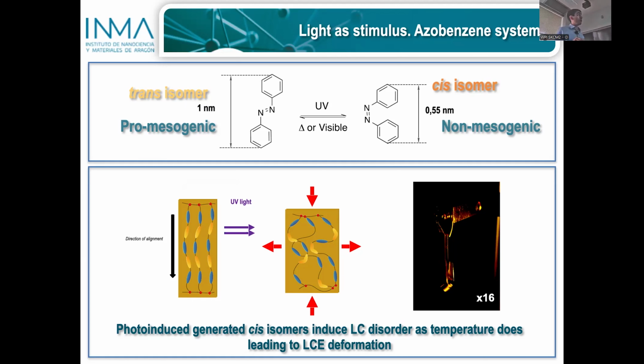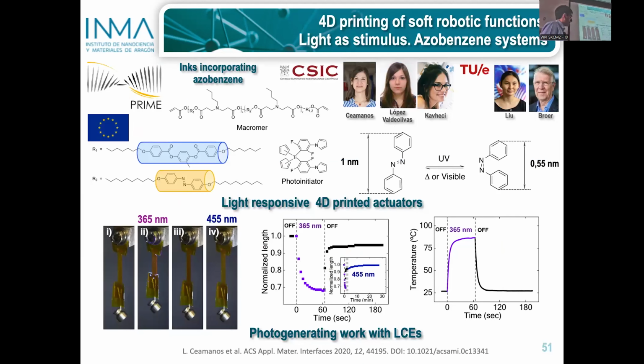So if we expose this to UV light, we generate a strong population of these molecules. If we now irradiate with visible light, or we leave it, or we heat it up, we go back to the pro-mesogenic shape. So we can incorporate this molecule in our materials. We expose to UV light, and then even with no temperature change, we expect that something like this will happen. And this was in the literature, but it was not done with this type of technology.